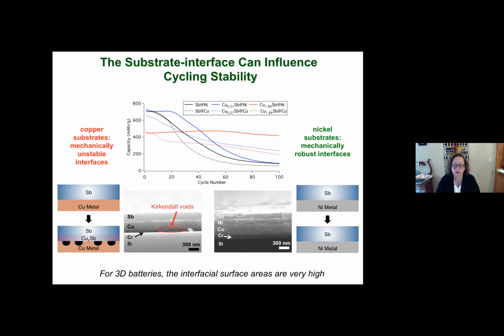So the plot in the top of the slide in the middle is capacity versus cycle number for a variety of compositions. So from pure antimony, low copper to copper rich on copper substrates and nickel substrates. And you can see that we can really tune the electrical conductivity of the anode, its mechanical stability with the substrate, and get pretty good capacity retention for a particular composition on a particular interface. And so this is really important then for being able to incorporate these materials into a 3D battery because the interfacial surface area is very high. So any degradation that happens at the interface is exaggerated in this kind of architecture.